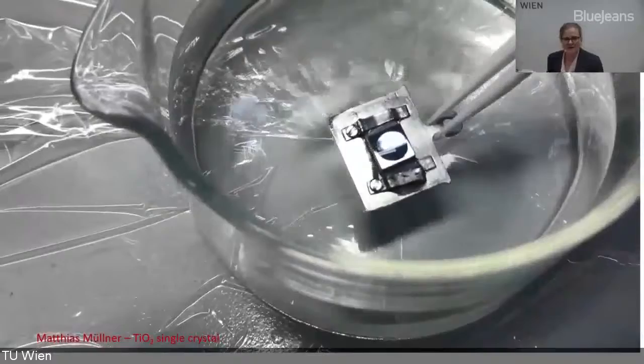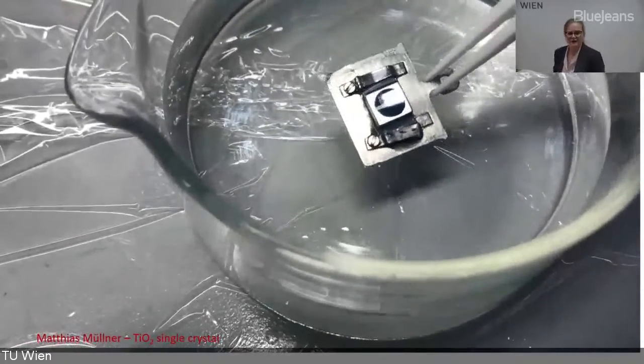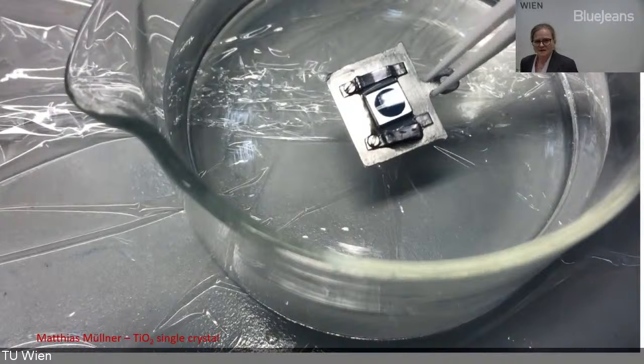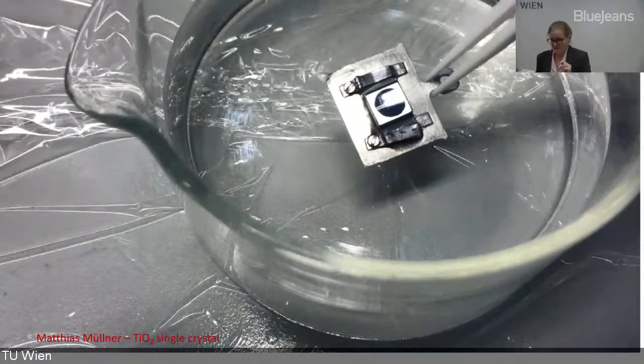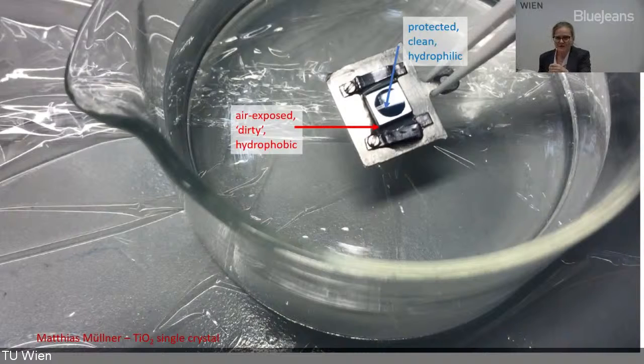I got this movie from my student Matthias Müller last night that hopefully reminds you why we use ultra-high vacuum in the first place. He was playing around with a TiO2 single crystal—you can see it put into a beaker and taken out again. What you can see is a little water droplet that's perfectly round. Why? Because this is where the surface was protected, so it was UHV clean and stayed clean and hydrophilic, whereas the surrounding area was just exposed to air for a little while and became dirty and hydrophobic. That's why we do these things, to keep things clean.